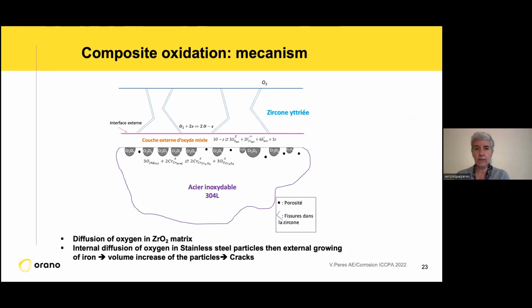I will not explain in detail, but we have this internal oxidation growth of chromium oxide, which is not very protective. That means that after that, some iron can go outside the precipitate, and with the oxygen coming from the zirconia, which allows easy transport of oxygen, you can have a growing oxide of iron and chromium outside the particle, and the cracks are coming from this external layer.